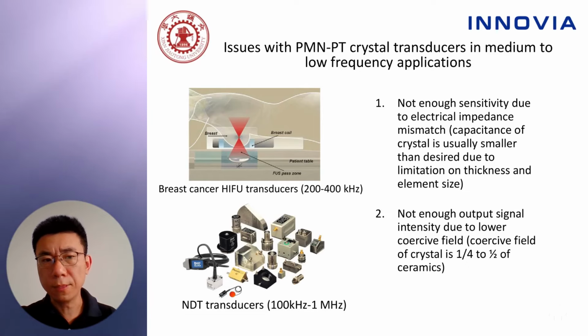These applications include breast cancer HIFU transducers, which are from 200 to 400 kilohertz in frequency, and high-performance NDT transducers, which are from 100 kilohertz to 1 megahertz in frequency. First issue, not enough sensitivity due to electrical impedance mismatch. The capacitance of PMN-PT crystal is usually smaller than desired due to their limitation on thickness and element size, limited by bandwidths.